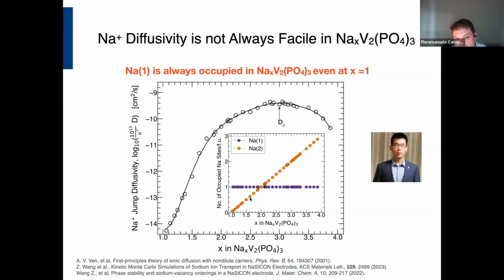But the second phenomenological aspect is this: I told you there are 2 sodium sites. One sodium site is octahedrally coordinated, and the other has a higher coordination number. As you start extracting sodium from a situation of sodium 4 all the way to 1, you can see that almost all the sodium is extracted from the sodium 2 site. Of course, there is an exchange between sodium 1 and sodium 2, but all the sodium is extracted from sodium 2, and here we are tracking the population of that site. So the last sodium is of type sodium 1, the octahedrally coordinated sodium. Extracting the last sodium is really the bottleneck, and it seems to be the crucial point here.